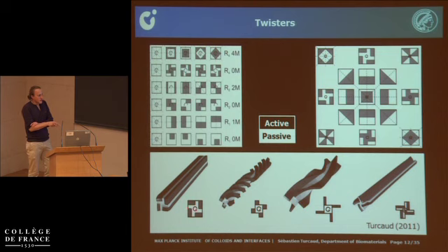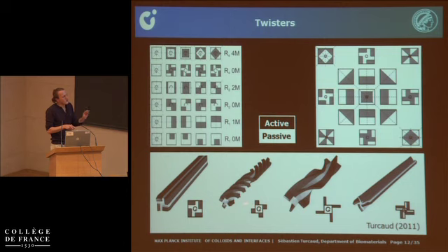And the results from the finite element analysis showed that having a structure with a rotational axis is not enough to actually observe rotation. In this case, even for very high contrast between the black expanding and the white resisting zones, nothing was happening, just stretching. But if instead of a closed cross-section I allow for some kind of wings, then we're able to create a twist. This twist can be tuned just by playing with the geometry of the wings: a rather small inertia would lead to a high twist, and a high inertia would lead to a small twist. Interestingly, this one in the end also doesn't work.